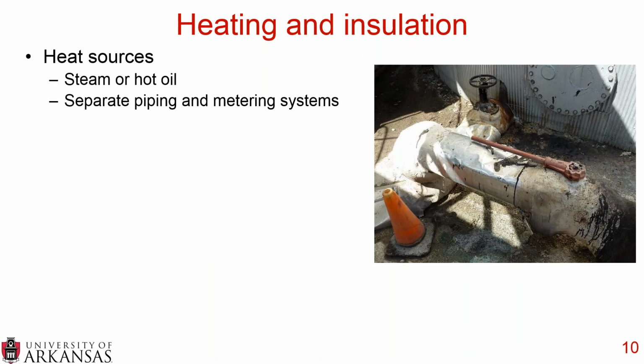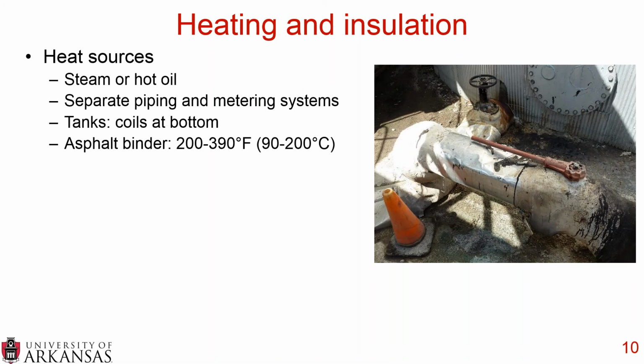Now, all tanks need some sort of heating and insulation. So heat sources can come either from steam or hot oil. And you want to make sure that this steam and hot oil has completely separate piping and metering systems than any of the asphalt emulsion or raw materials going into the asphalt emulsion. So when you're walking around a plant, there's actually two completely separate sets of pipes. And that's because one has to do with the asphalt emulsion and one has to do with the heat, whether it's steam or hot oil.